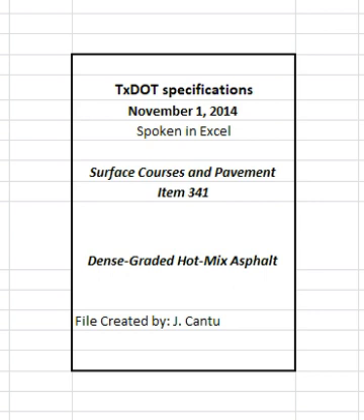4.9.3.3.3 Longitudinal joint density. 4.9.3.3.3.1 Informational tests. Perform joint density evaluations while establishing the rolling pattern and verify that the joint density is no more than 3.0 pcf below the density taken at or near the center of the mat. Adjust the rolling pattern, if needed, to achieve the desired joint density. Perform additional joint density evaluations, at least once per sublot, unless otherwise directed.